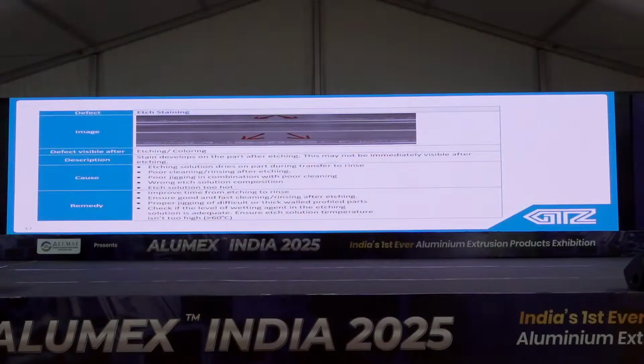Staining: it is visible after etching and coloring. The main issue is etching; higher etching solution dries on the part during transfer. If the time gap between etching and rinsing is more, then this could happen. Also, wrong etch solution or etch temperature being too high. So for remedy, improve the time lag between etching and rinsing, and temperature should not be greater than 60 degrees.